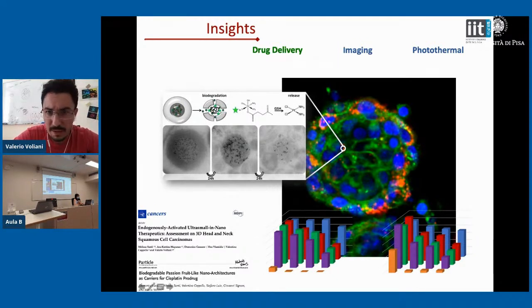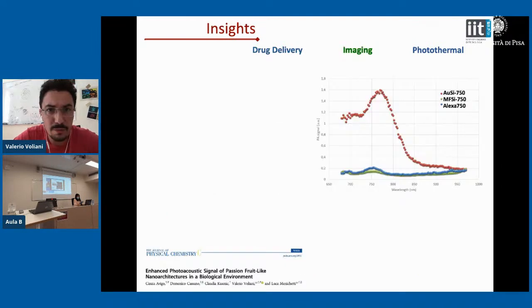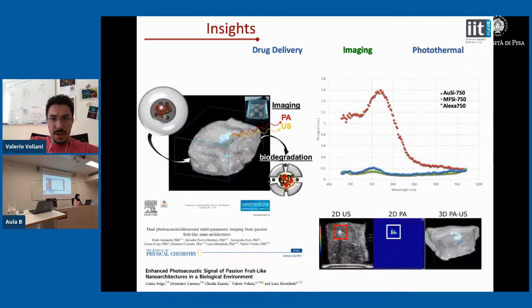And we have tested our nanoarchitectures in the 3D models that we have developed inside my group. Then we have also inserted dyes inside the cavity of the nanoarchitectures, and we employed the quenching effect of the gold nanoparticles in order to compose some photoacoustic probes in the IR part of the spectra. Moreover, we were able to conjugate the photoacoustic behavior with the ultrasound one. This is thanks to the impedance mismatch of the silica shell. So in this way, we obtained a light in, sound out, and sound in, sound out probe.